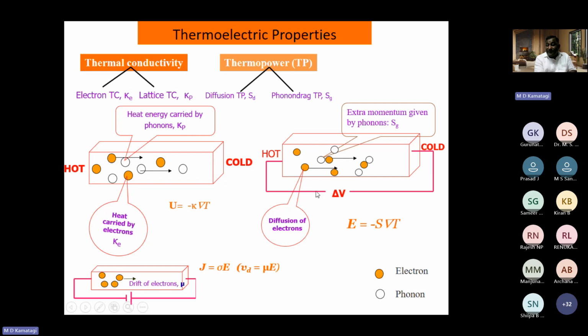Also, phonons will diffuse because of the temperature gradient. They may give an extra momentum. Suppose that this electron is moving in this direction and another phonon comes and hits it, so that this electron will gain an extra momentum. And this contributes to a phonon drag thermopower. This phonon drag thermopower is significant only at liquid helium temperature or less than 20 K. After 20 K, the phonon-phonon scattering becomes more prominent.